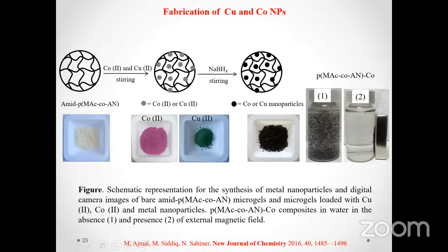And here is the pictorial and graphical representation of this experimental setup. In the first step, we prepared these hydrogels, which were off-white colored, and they were modified, converting nitriles into the amido oxime groups. Then they were used as reactors for the absorption of cobalt and copper metal ions, and very strong absorption of copper and cobalt was observed, as can be seen from the intense colors of these metal ions.